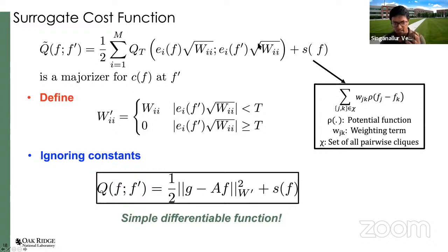So you start with the reconstruction, project it, and find the error between the measurements and your reprojection. If that error is very large, you essentially reject that measurement in the next inner iteration. If it's small enough, where small is defined by some threshold, you set it to the original weight. Essentially, by using this kind of penalty, we've turned the problem into a sequence of regularized weighted least squares type problems, where the weights are changing on the inner iterations.